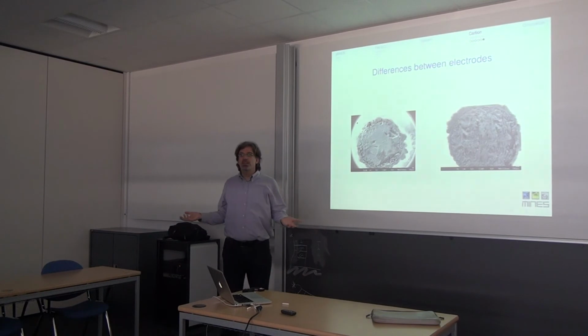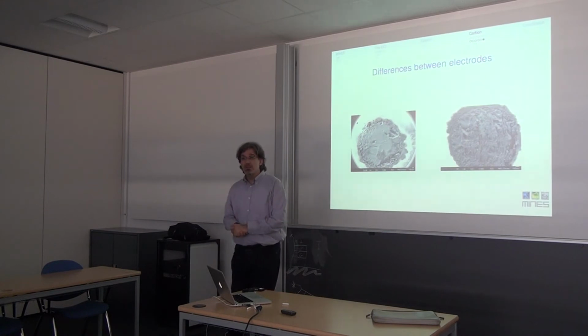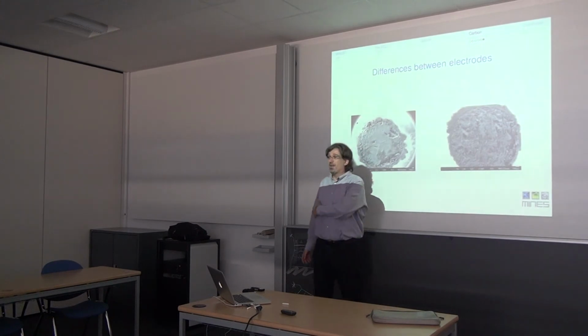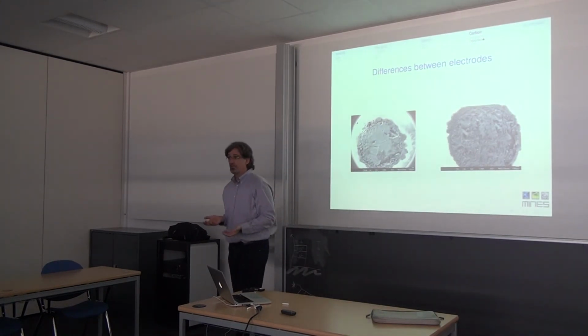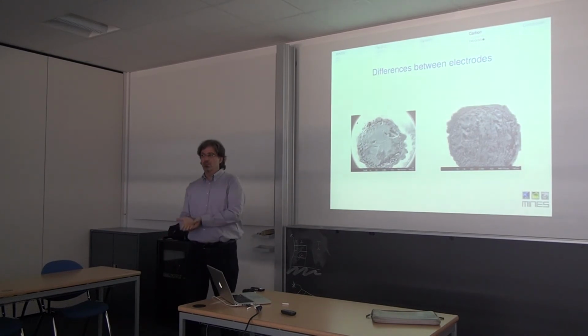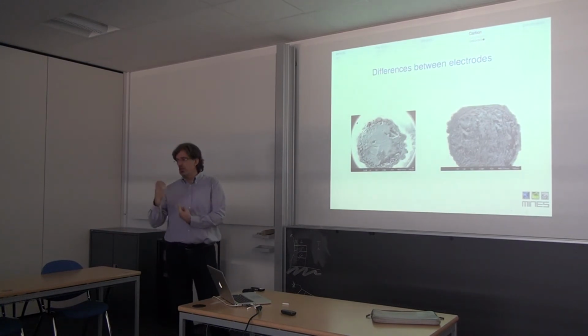The surface is a mix of carbon nanotubes. But on a 1 millimeter dimension, of course, the carbon nanotubes present on the surface, I cannot count the number. So, the idea is good, because I have a very high efficiency. I have this type of interesting emission, periodic emission, but with these dimensions, the reproducibility is impossible to have.